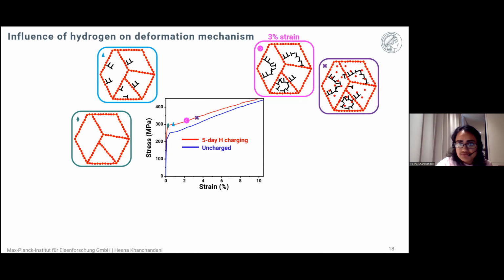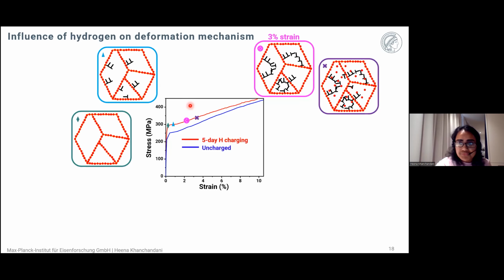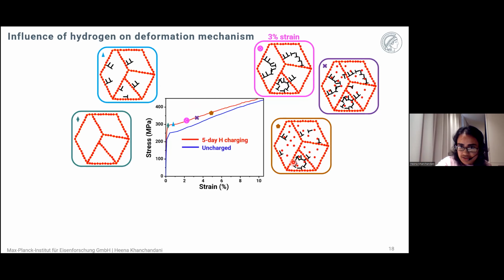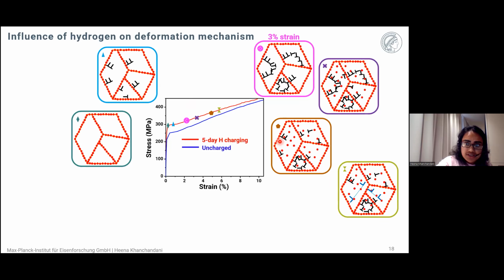And then when we further increase the load, there is a redistribution of hydrogen in the microstructure, because there are more dislocations which are nucleated from non-planar slip systems. This redistribution of hydrogen in the microstructure breaks these dislocation cell walls, and it nucleates the stacking faults locally, because this redistribution of hydrogen creates regions with lower and higher hydrogen contents. There are regions which are depleted of hydrogen, and there are regions which are enriched in hydrogen. And hydrogen reduces the stacking fault energy. So in the regions which are enriched in hydrogen, stacking faults are nucleated locally.